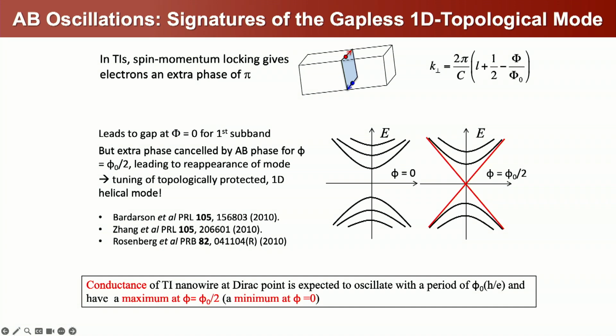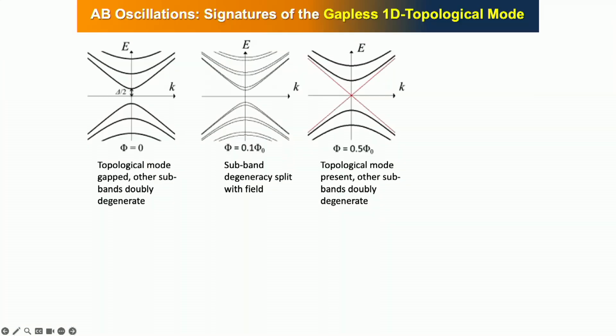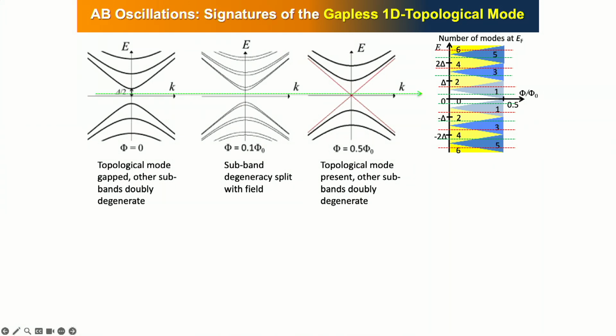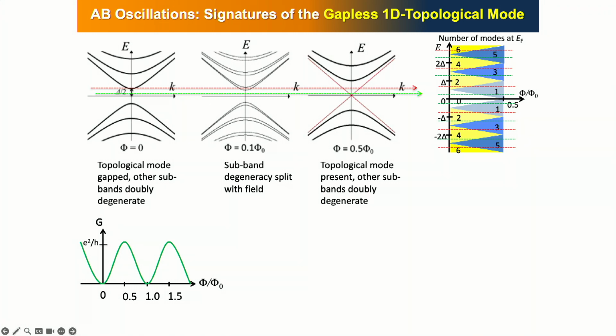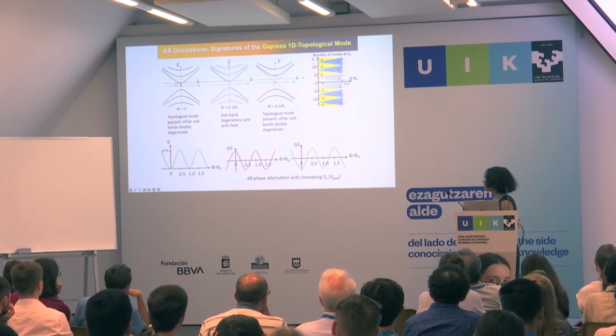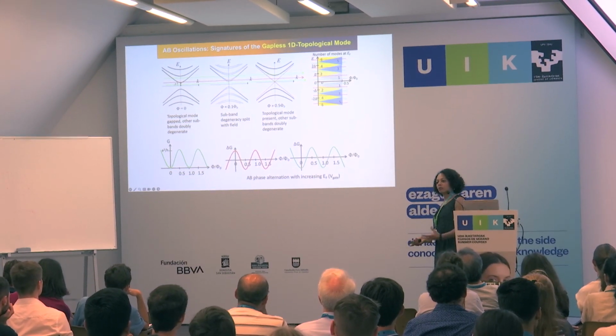And then finally, because we're tuning as a function of magnetic field, we're gapping out this topological mode. You expect to start out, as you apply fields, with a gapped mode and end up with the mode that's present as you apply half a flux quantum. So if you measure conductance as a function of applied field, you should see something that goes from a minimum at zero to a maximum at half a flux quantum. But then as you take another cut that cuts through different bands, you should see that oscillate. You should go to a max at zero to a minimum as you start splitting those bands, and then that alternates again. So you should also expect to see phase alternation. This is just a function of seeing 1D subbands in this system, which is also something that would be interesting.